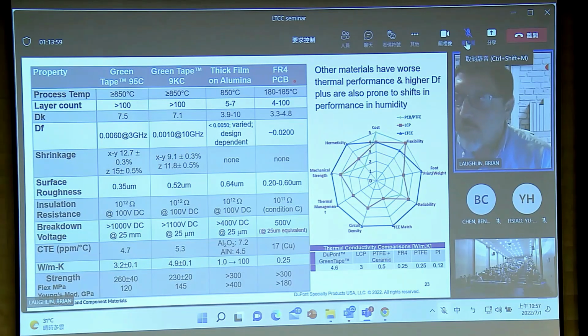And then I also put on here the ubiquitous material, which is pre-preg epoxy FR4. So here you're processing at much lower temperatures. You still have multi-layer capability. The dielectric constant is typically a little bit lower, just because organic materials have a lower dielectric constant than ceramic, but the dielectric loss is an order of magnitude or more worse. And so printed circuit boards are great because they're cheap, ubiquitous, and easy to access, but they're not going to make good high frequency designs that give high efficiency devices.